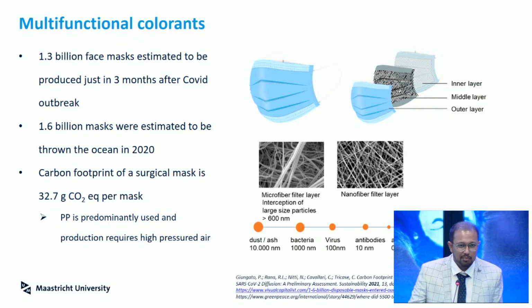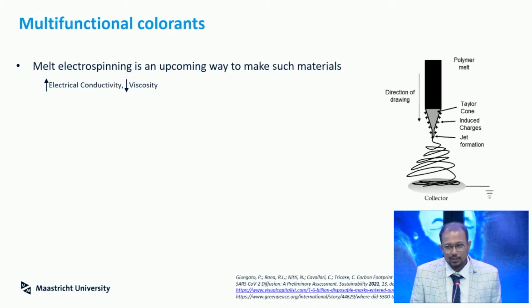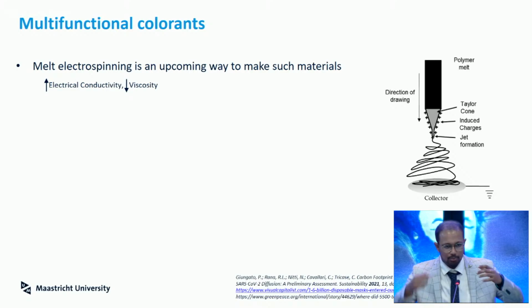Luckily, I had a colleague who finished her PhD two years ago, and she was working in a process called electrospinning, which can also be used to make such thin fibers, because for masks you need good filtration, which means you need fibers in the micrometer or less than one micrometer range. This process is now upcoming and developing to produce such fibers. You take a polymer melt in a syringe, push it through the nozzle, and have a collector plate that is charged. The polymer interacts with the electric field and gets stretched to form yarn, or filaments. What we needed here was good electrical conductivity and good flow behavior, which meant lower viscosity.